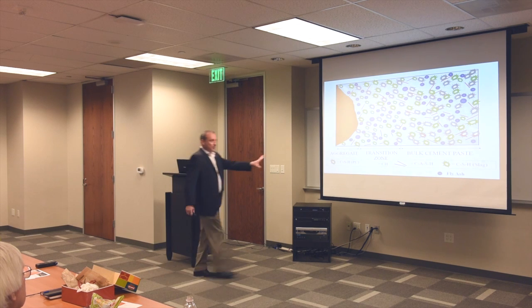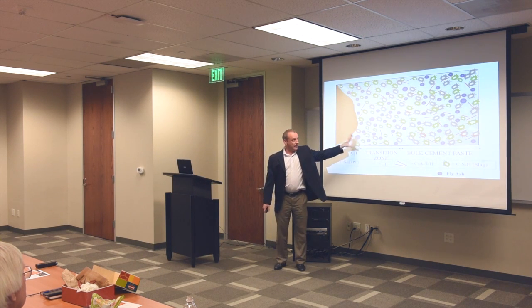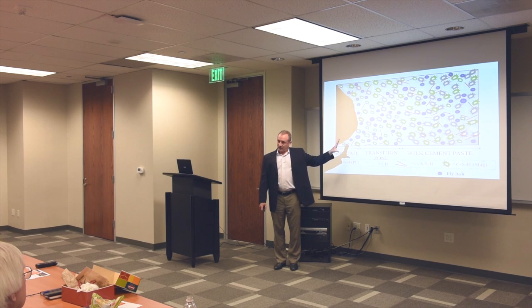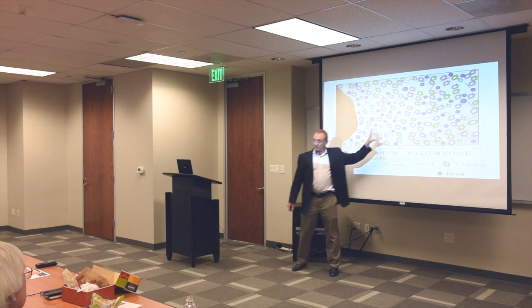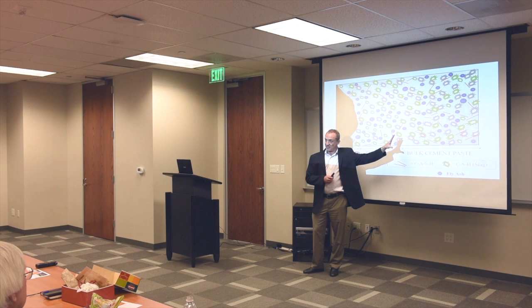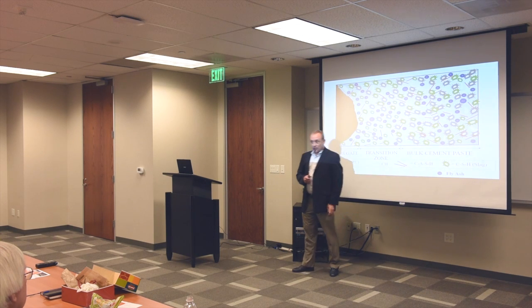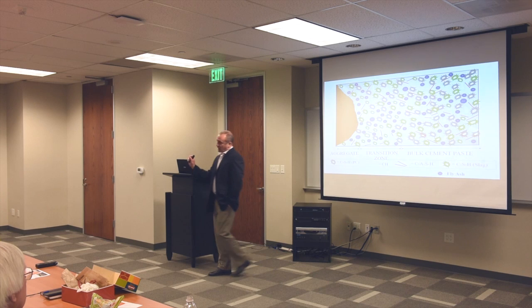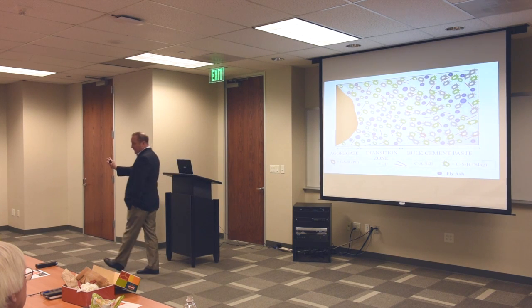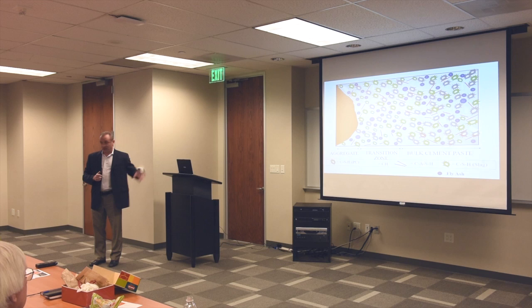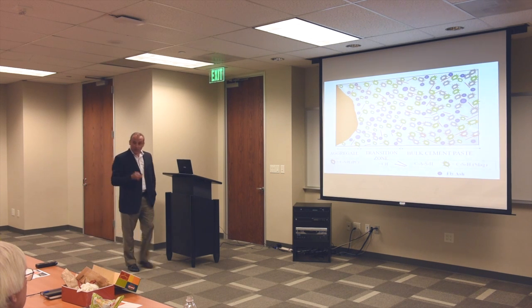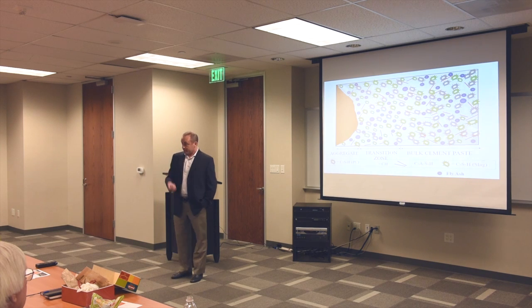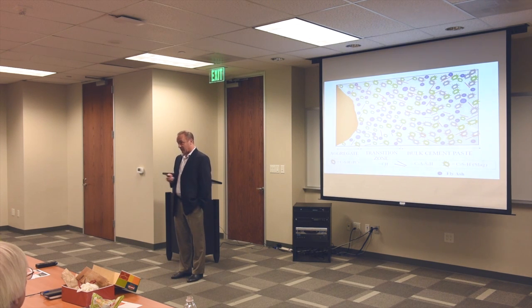Here's an example where we've put fly ash and slag in this kind of simulation. Now you can see that the region around the rock looks identical to the region away from it, which we refer to as the bulk paste. So by segmenting the porosity so that water can't travel through easily, and taking care of this weak region, we can reduce the levels of water and salt ingress by orders of magnitude. This is really the way we've been able to have such good infrastructure in our state compared to other states.